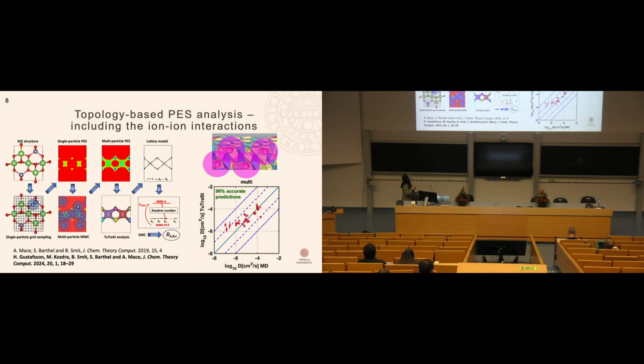The output of this gave us this multi-particle potential energy surface, which really improved the prediction of the potential or free energy landscape felt by the lithium ion. And then this multi-particle grid, in the same way as before, is analyzed by the topological analysis to create our lattice model and compute the diffusion coefficients. And here we got a significantly improved prediction of our diffusion coefficients in the ionic material.